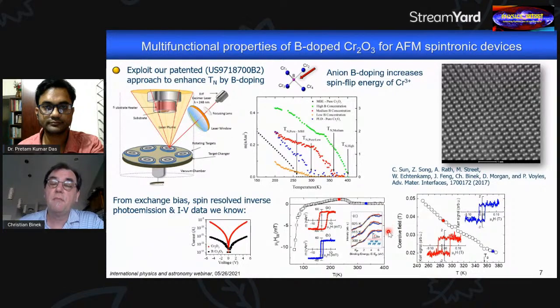And that had something to do with the anisotropy of the system. The boundary magnetization apparently was no longer perfectly perpendicular to the film plane. We confirmed this by growing an in-plane exchange bias system, where the ferromagnet has its easy axis in the plane rather than perpendicular to the plane. And indeed, some exchange bias came back in that geometry. But that was not useful for us. Also, we did inverse spin-polarized photoemission, showing that this material is indeed still magnetoelectric. You see that by the spin splitting here, and that the spin splitting kicks in already above 307 Kelvin. So that is good news. But it also told us that indeed the boundary magnetization is canted and not perpendicular anymore.